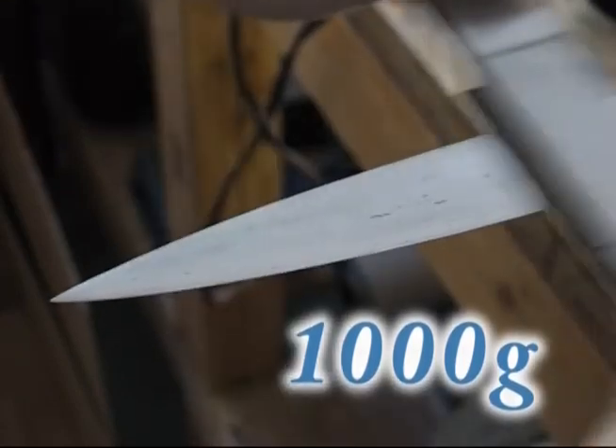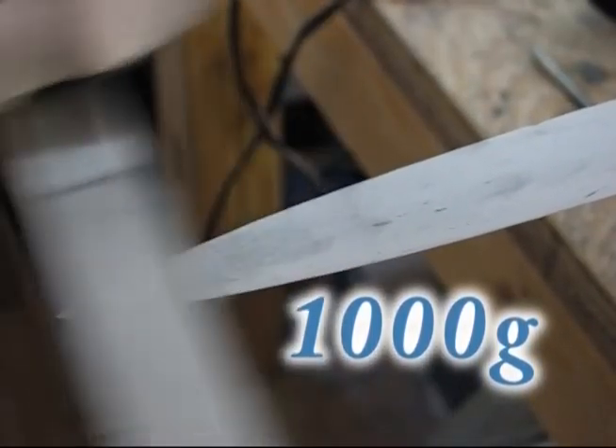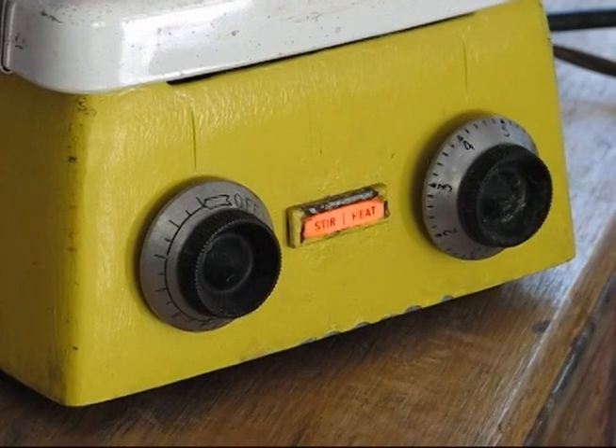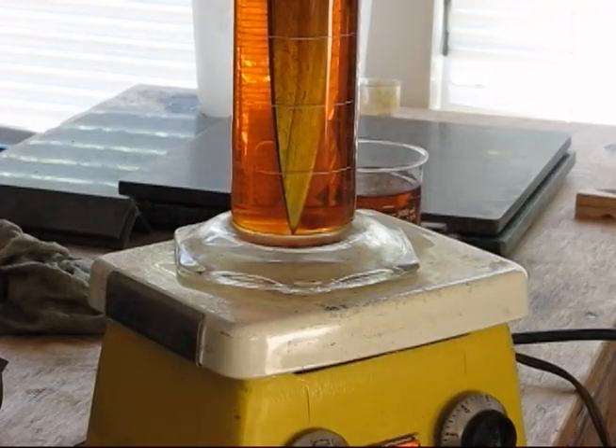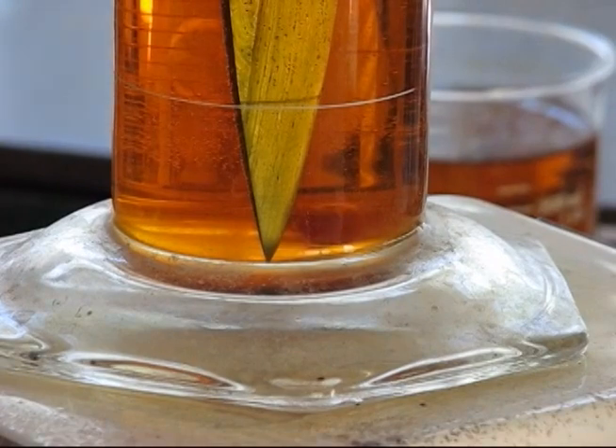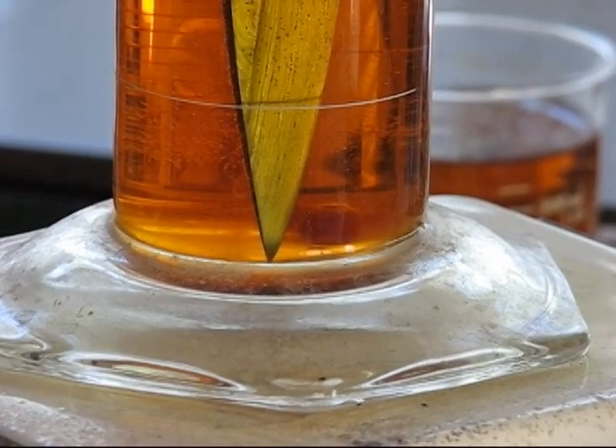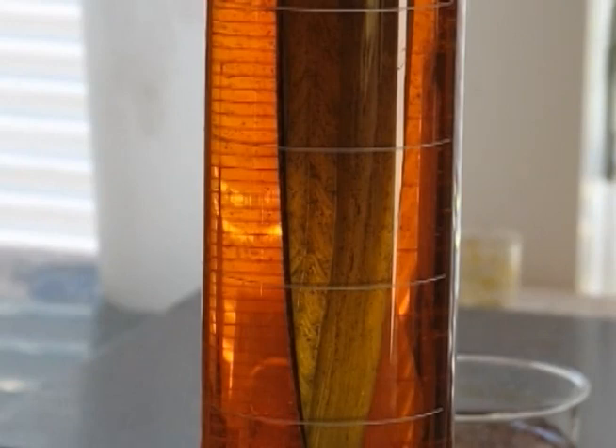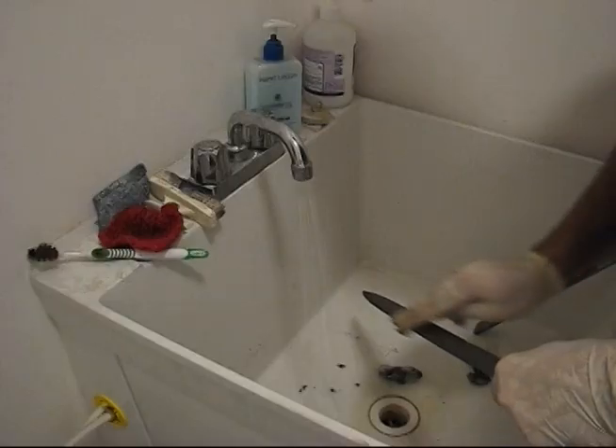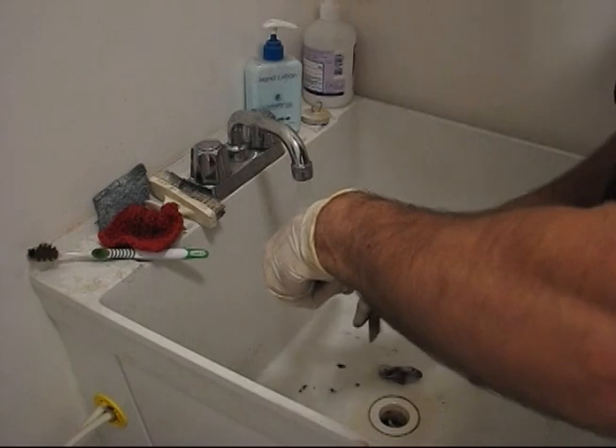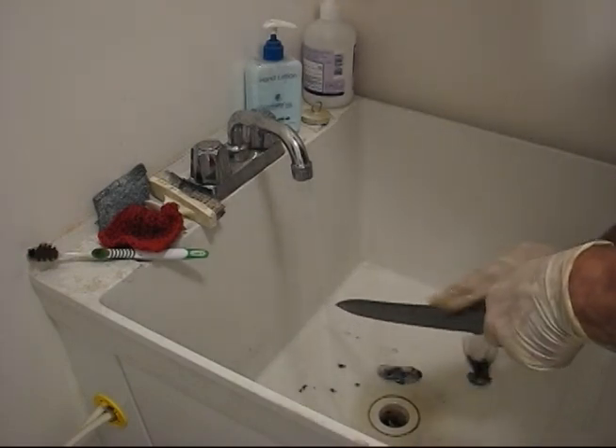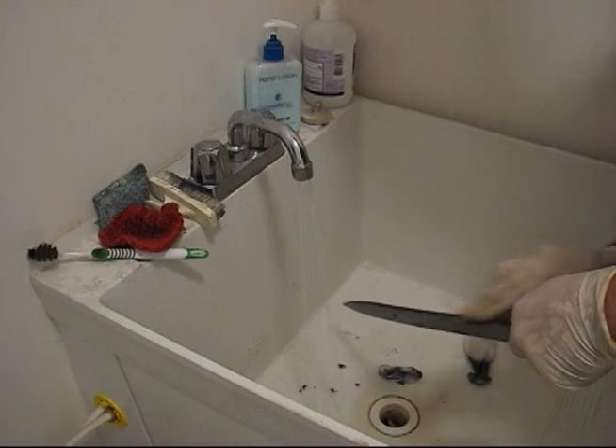As the blade will be etched in acid, Jesus will stop at 1000 grit. The blade is ready to reveal its character. This is the most exciting moment. A solution of diluted ferric chloride is contained in a vessel that will withstand heating, using a hot plate that also contains a stirring magnet. After some minutes in the solution, the pattern of the metal becomes visible. The oxides are washed away with hot water, and the acid is neutralized with a baking soda solution.